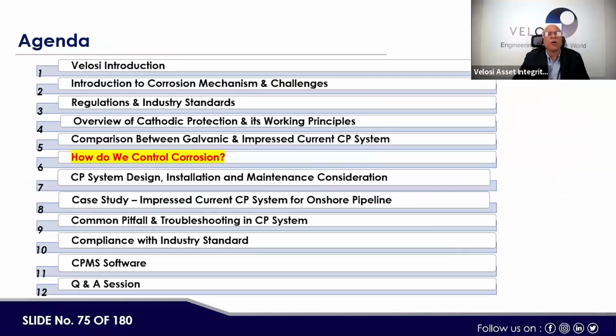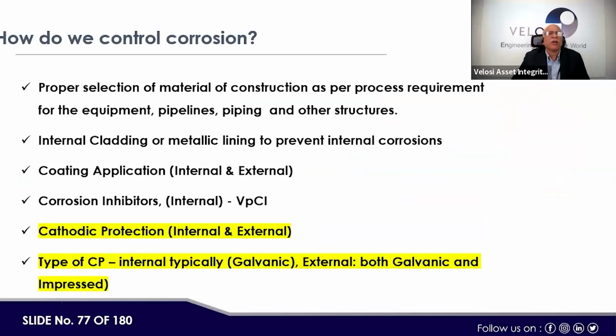Its utilization. Now, here, how do we control corrosion? I touched this subject earlier also when I started my presentation. But in general, proper selection of material of construction as per process requirement for the equipment, pipelines, piping, and other structures, internal cladding or metallic lining to prevent the internal corrosion, coating application, internal, external. Then corrosion inhibitors are being injected to control the corrosion. Then this cathodic protection comes. Internal, external, both can be used. Type of CP internally, typically galvanic. It could be generally, typically, but it can also be ICCP in the bigger tanks.